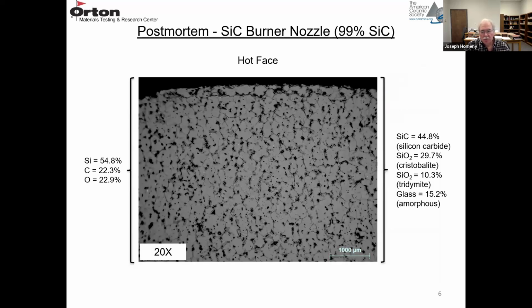So the burners, if they're gas fired, can be various compositions. They're usually a high alumina. They can also be a silicon carbide. So this is a post-mortem of a burner nozzle. This is a 99% silicon carbide material, and this is a 20x magnification of the hot face.